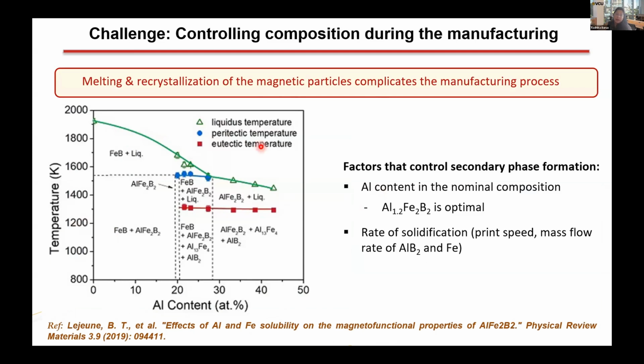That is a big problem with DED, because melting and recrystallization of the magnetic particles tends to complicate the manufacturing process. For all magnetocaloric materials, such as AlFe2B2 shown here, you have a very tight tolerance. This is a pseudo-phase diagram of AlFe2B2, and only within these dotted lines will you see the magnetocaloric response.